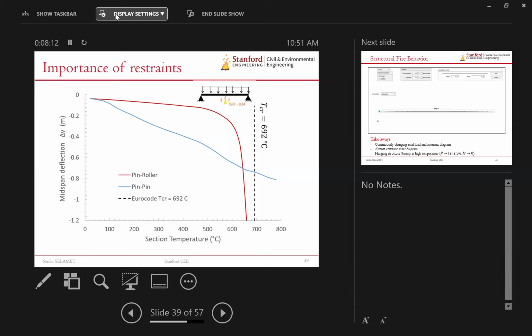But when you change only one thing, from pin roller to pin on one boundary, it can now develop compressive stress inside. If it goes into runaway, it basically stops the beam from failing in runaway motion because it's being held by these two supports, axially and vertically, translationally. So you can see that you get more deflections because there is a compressive force developing, and it's pushing the beam down.